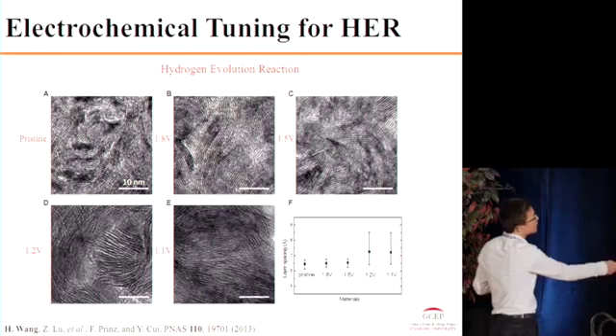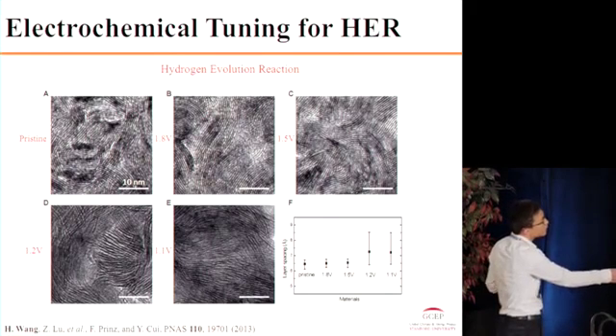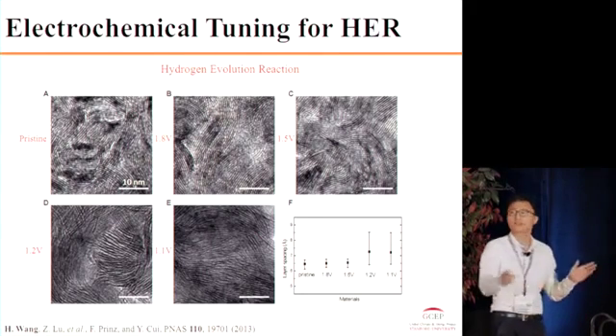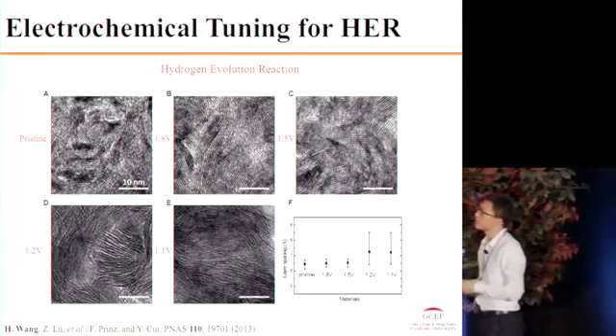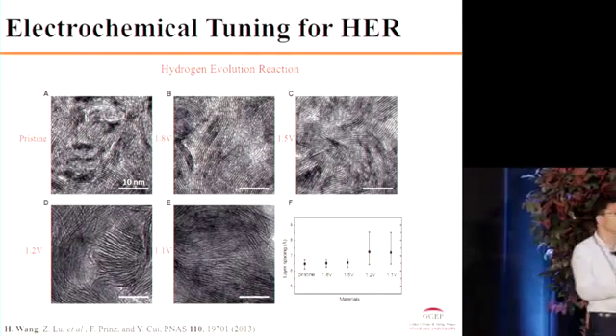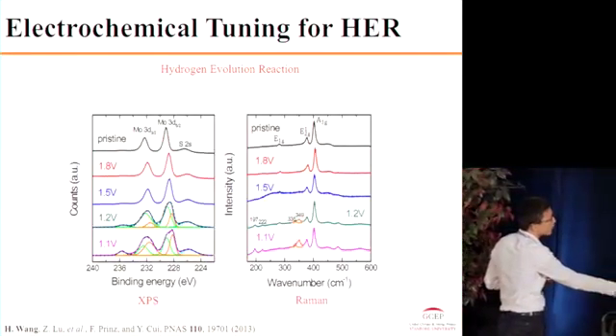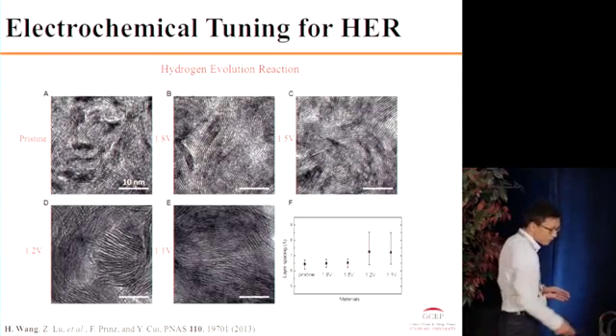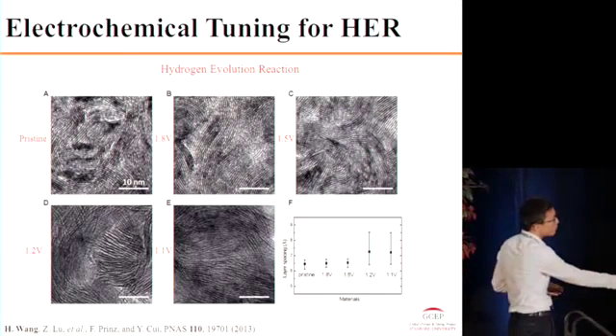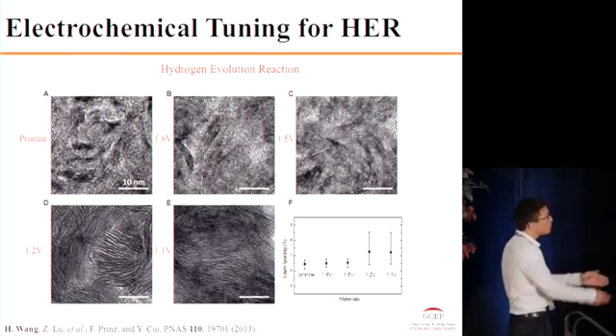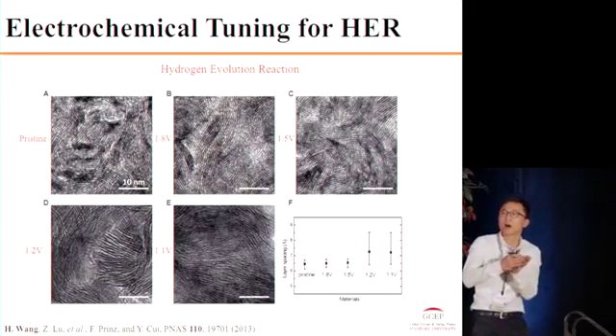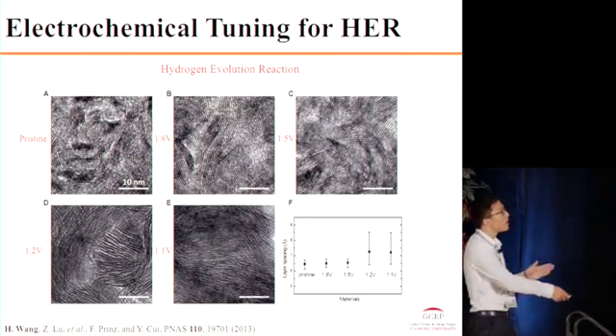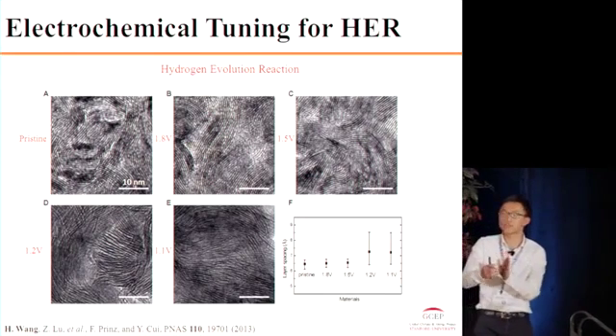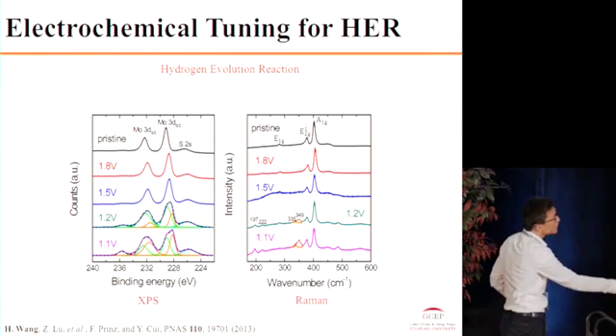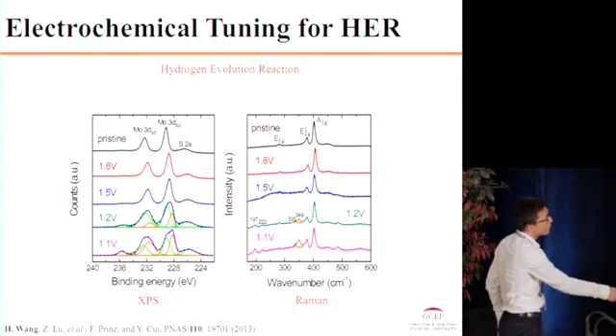As we can see, for the pristine molybdenum sulfide down to 1.8 and 1.5 volts, there's really no change to the structure of the thin film. But if it goes to the phase transition regime, 1.2 volts and 1.1 volts, you can see these layers are partially exfoliated with a much larger layer spacing. And also the electronic structure changes a lot.